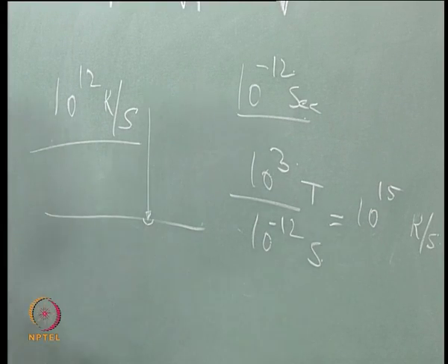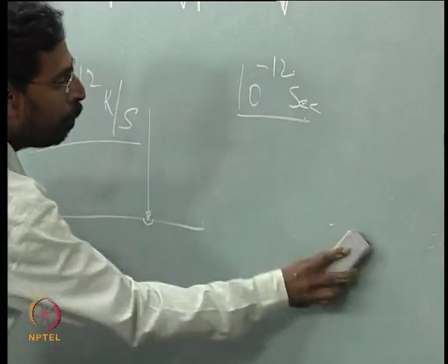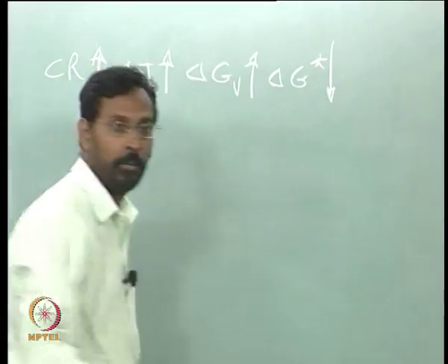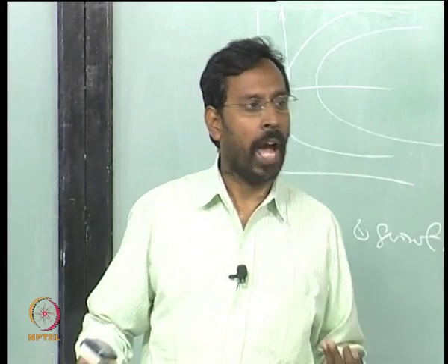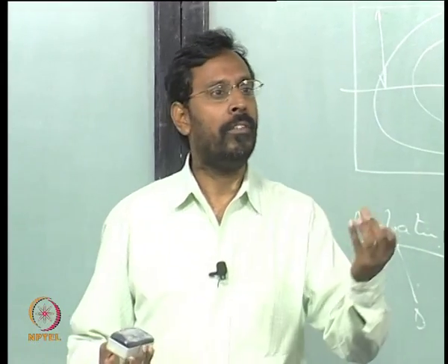So in principle you can get those cooling rates, and with that people have shown that even pure nickel can be made into a glass. People have made glasses like that. That means the time available is so short for the atoms to even form a crystal.